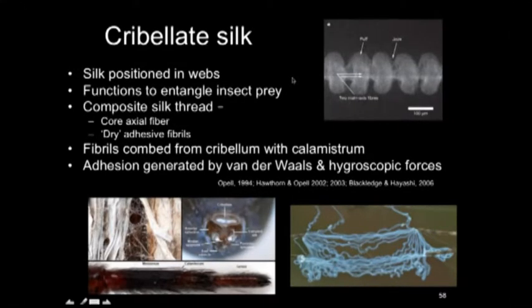And spiders produce them through a combination of a specialized set of glands and a comb called the calamistrum on their hind legs. As they comb them out, that causes these puffs. And so instead of operating on a glue, they use van der Waals forces and hygroscopic forces. So these van der Waals forces are just near-molecule forces where you have a difference in charge between the molecules, and hygroscopic forces are obviously sort of capillary forces, as they can use water.